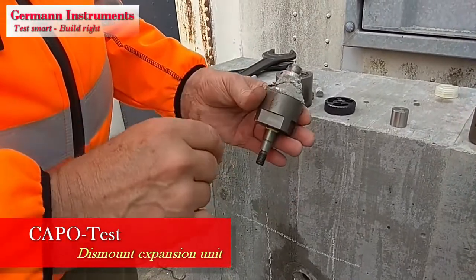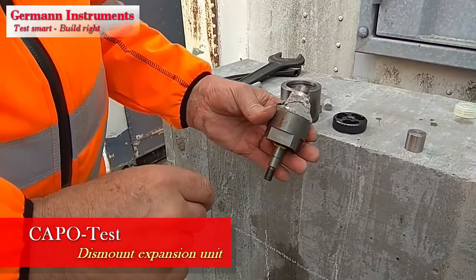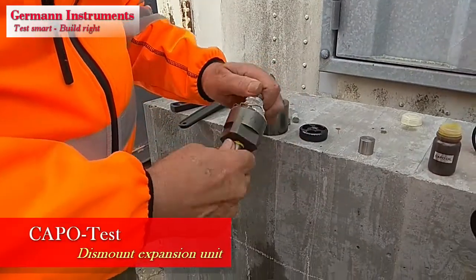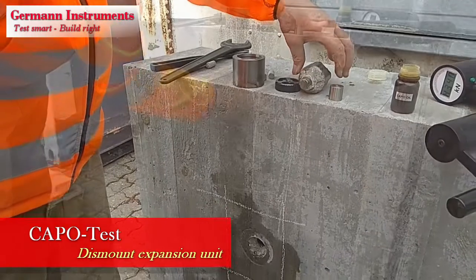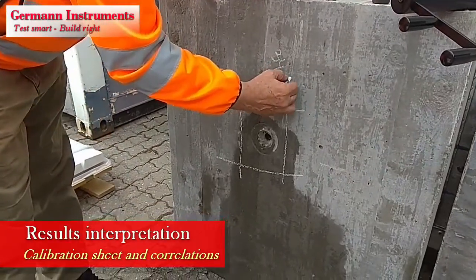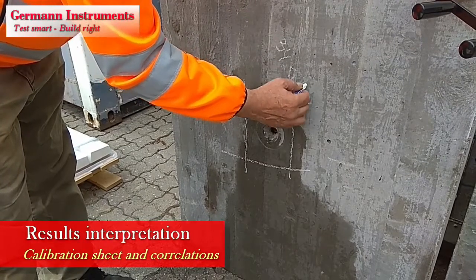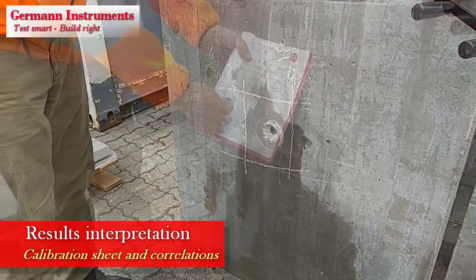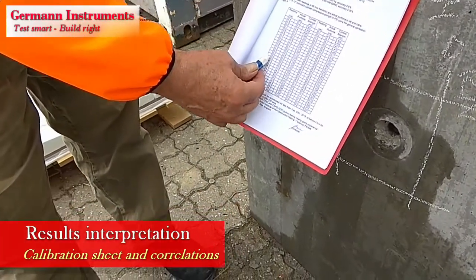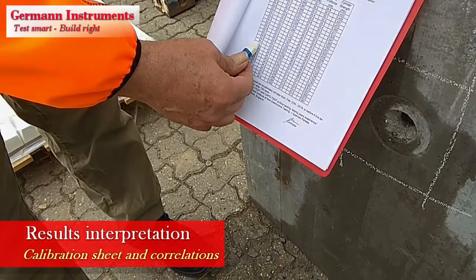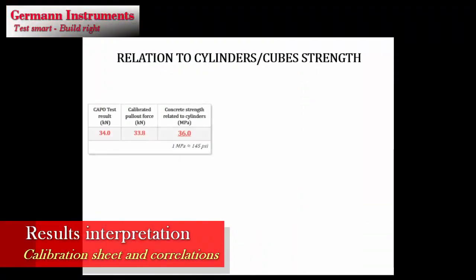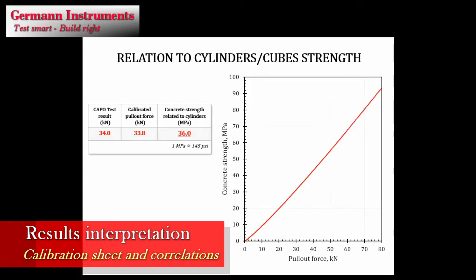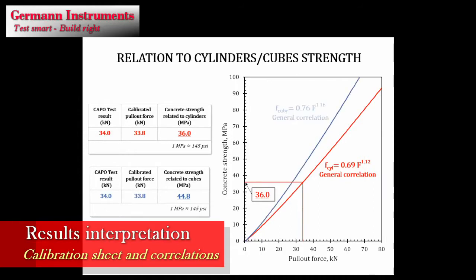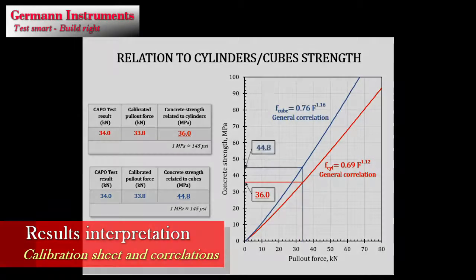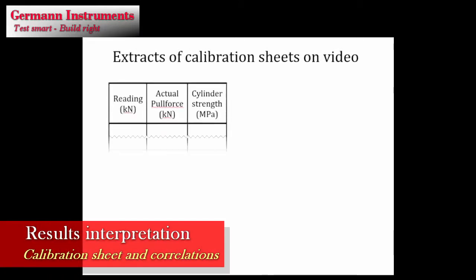The expanded steel ring can be compressed again using a C111 resizing tool set and reused 2 to 3 times before it breaks. The maximum pull force is written on the concrete surface in kilonewton and correlated to either standard cylinder strength or to standard cube strength in megapascals or psi. Using the instrument's calibration table, the compressive strength can be obtained relating the calibrated pull force to strength on standard cylinders or cubes, following the general correlations.